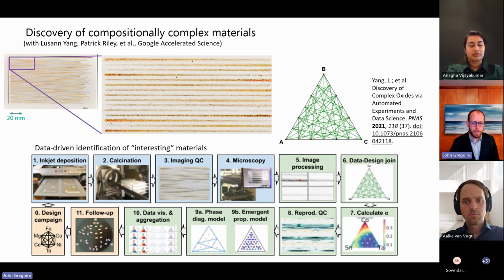A very different approach is a project we did with Google Accelerated Science, where we printed these continually varying composition lines that essentially were like a laser grid rastering through composition space, and by applying some models to that, could sometimes identify phase boundaries by changes in optical properties. More often, we found very useful a metric for essentially saying the probability that these three elements are interacting in a way that produces properties that are completely distinct from any one or two element combination.